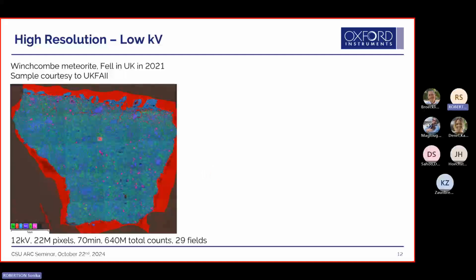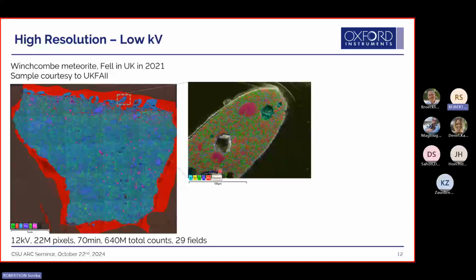Example data, this was like a 70-minute acquisition. There are 30 different fields of view stitched together, 640 million total X-ray counts. That's a lot. And this was done at 12 kV, by the way. And you could zoom in. This is 100 micron scale bar. There's aluminum, nickel, iron, silicon, and magnesium.